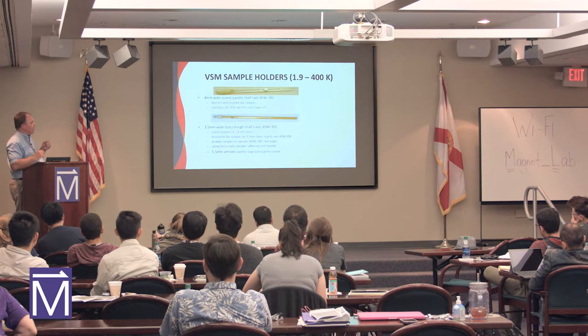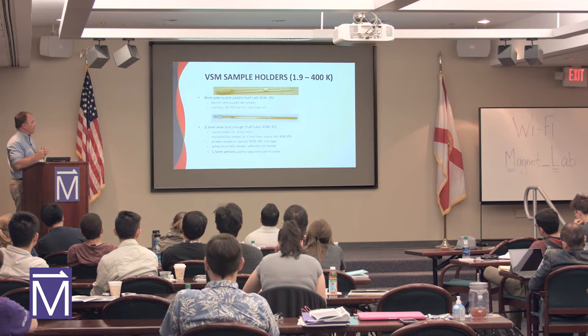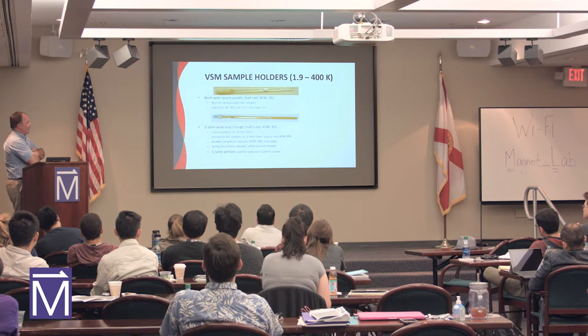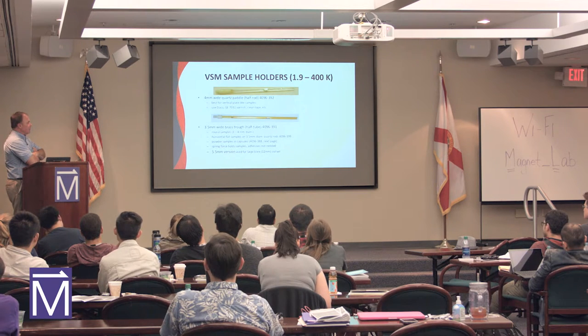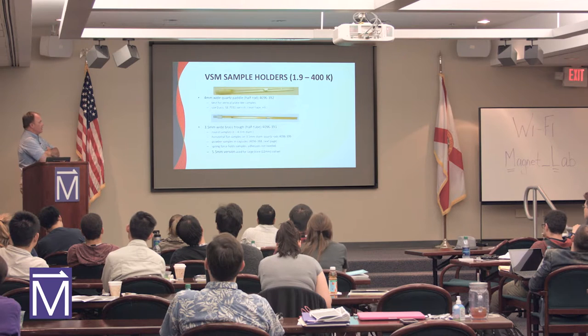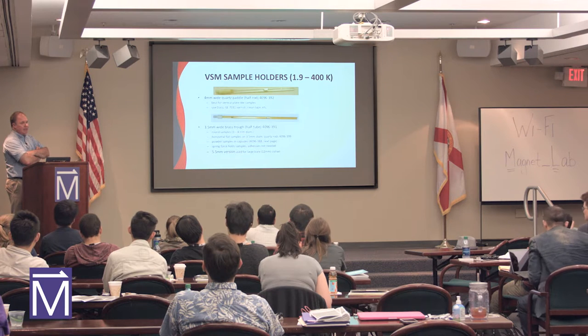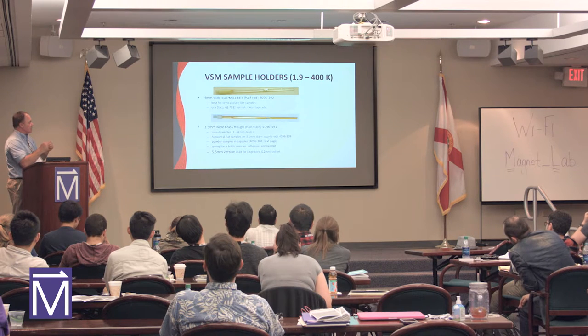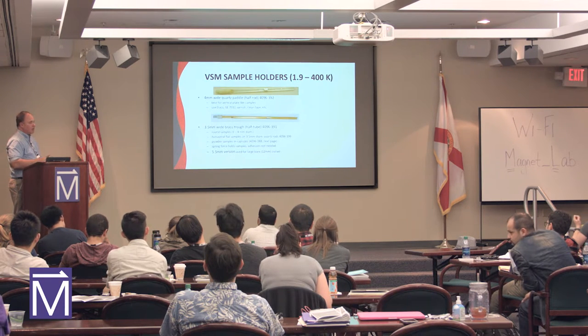VSM sample holders, you'll see this in the lab. We've got a quartz paddle. Mount your sample to the quartz paddle with some varnish, cement, some tape, Kapton type tape. We've got a little brass holder with a couple of capsules that hold the sample in place. There's also a little powder holder where you can put powder inside and hold the powder inside the part of this vessel and clamp it together. So the brass tube sort of holds it mechanically in place.